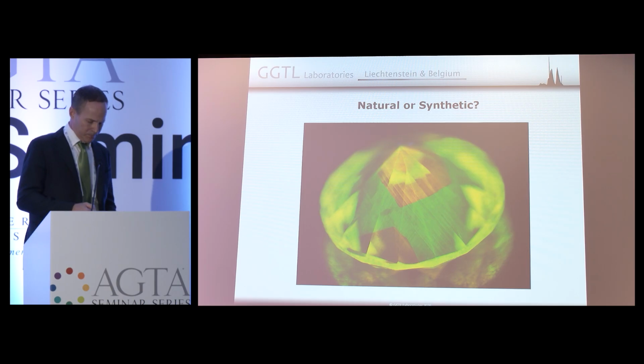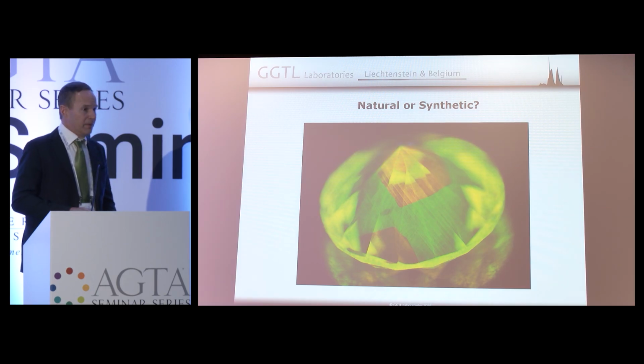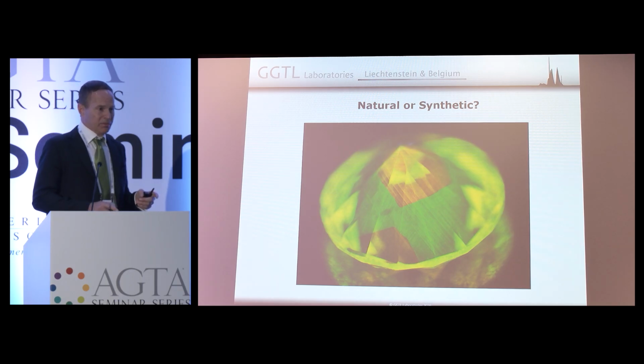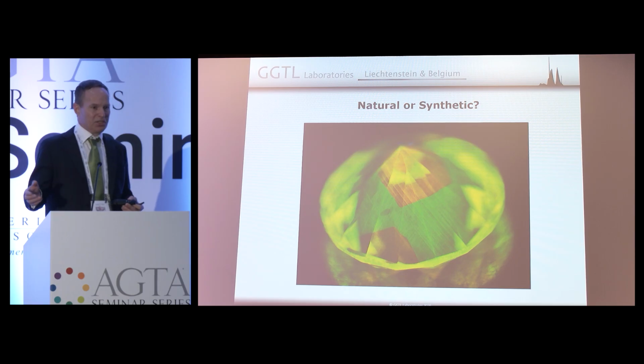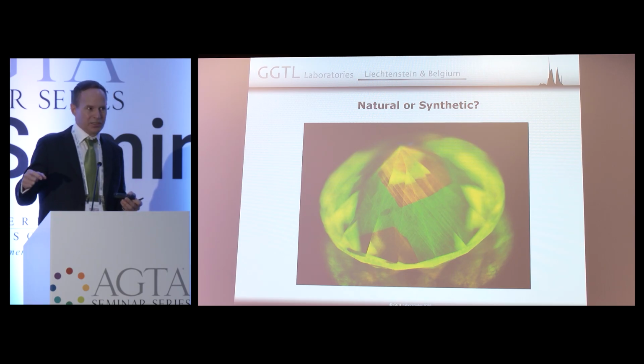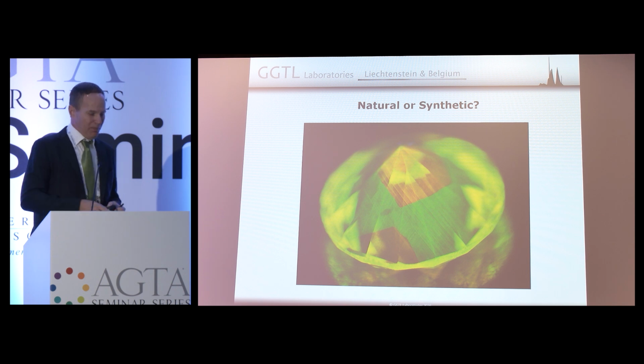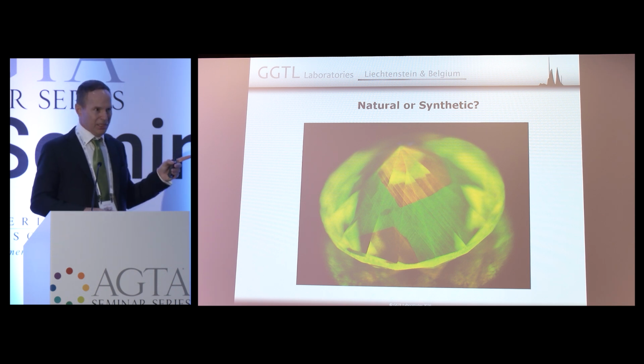So if you saw this at 220 instead of 250, 254, you would think differently? No. What you do is you go basically long wave, then shorter, until you're at deep UV. So we're having 6 excitations, and the sequence of those 6 excitations usually gives us a straight conclusion, natural or synthetic. But the image itself can be really disturbing.